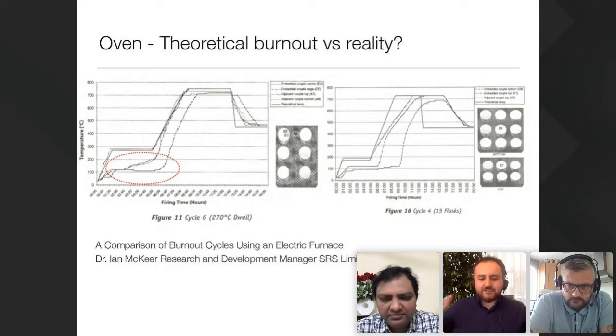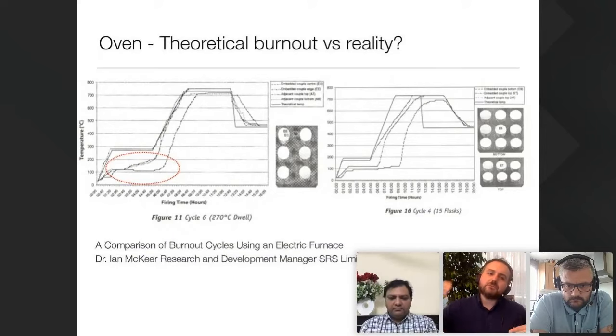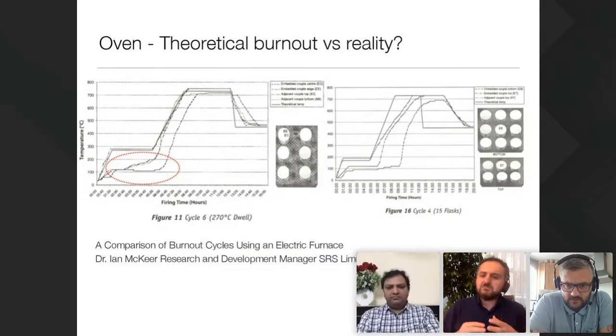And then with the heat, which comes from outside of the investment towards the inside, because your oven is heating from outside, the walls start boiling. The evaporation pressure goes through inside, and on the walls of the cavities inside, what happens is that you have breakage happening, like some chips going, right? So the faster you do this first step, you may have more pressure in the evaporation.